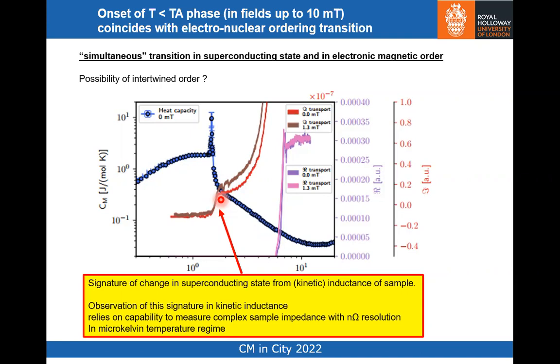So you could be in a world where applying the magnetic field, inducing this in-plane component parallel to the magnet, is just complicating the issue. And the cleanest system is this one that you're looking at now, where you have a very sharp peak in the heat capacity. You just have this antiferromagnetic order without anything else happening in the magnetism, and you have the superconductivity. So this is probably the most fertile place to be thinking about the intertwining of the electronic order, and it just gets messed up as you go up in magnetic fields. That's how I think about it. Let's understand this feature, that's part one, and then how it all disappears is probably a more complicated story. That would be my sort of methodology there.